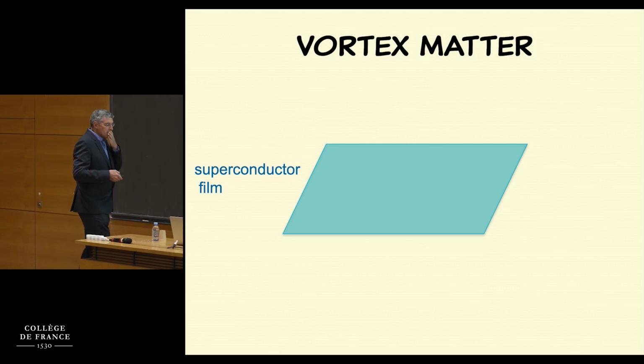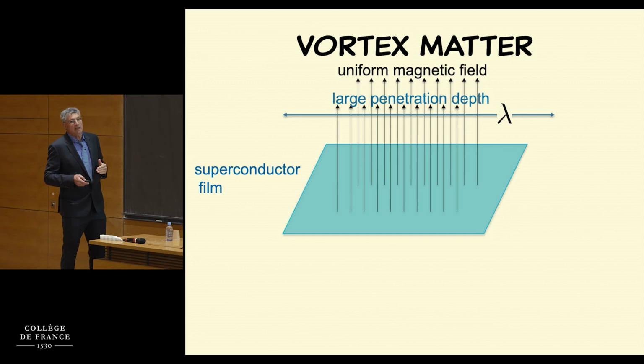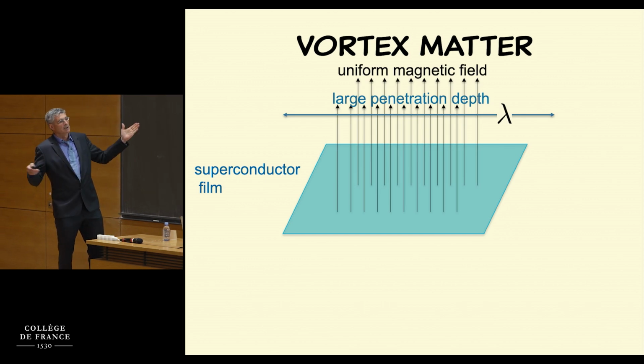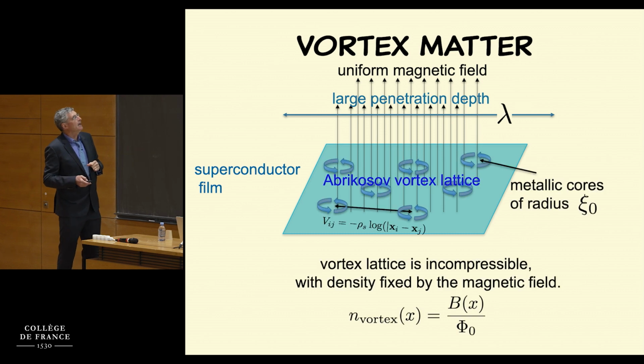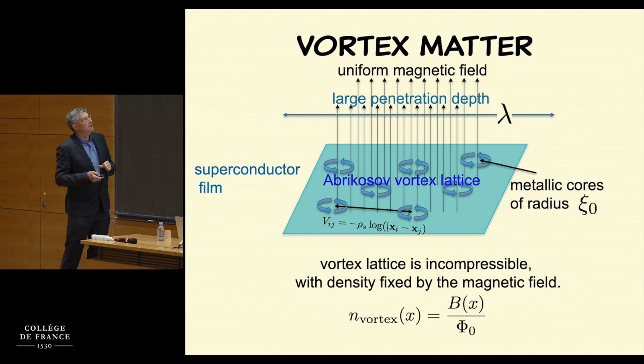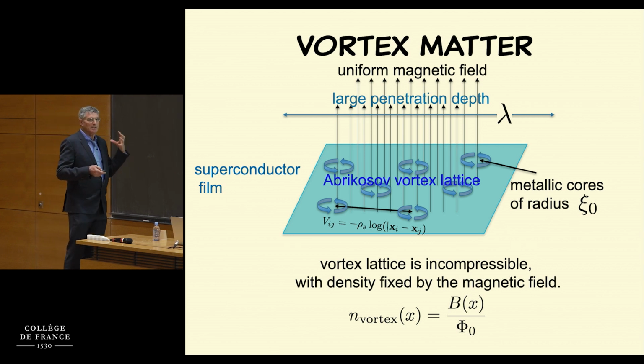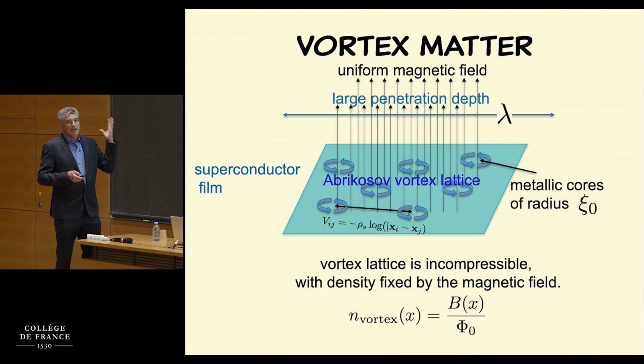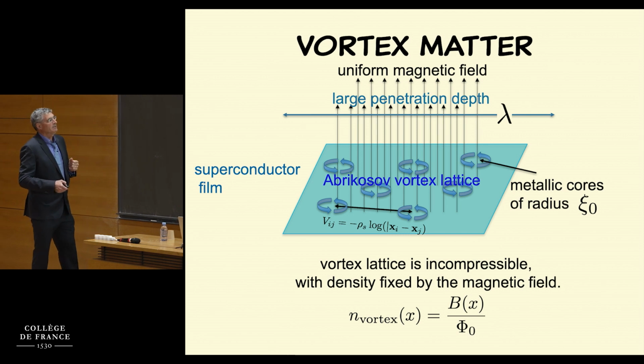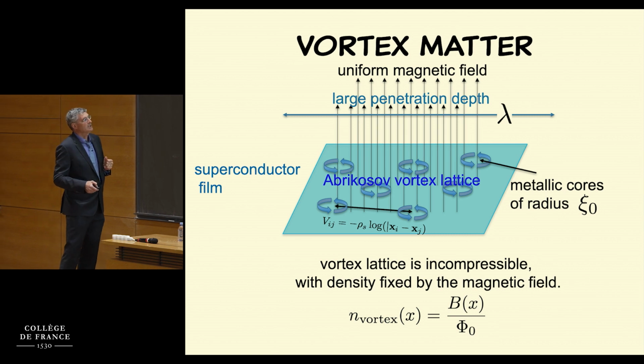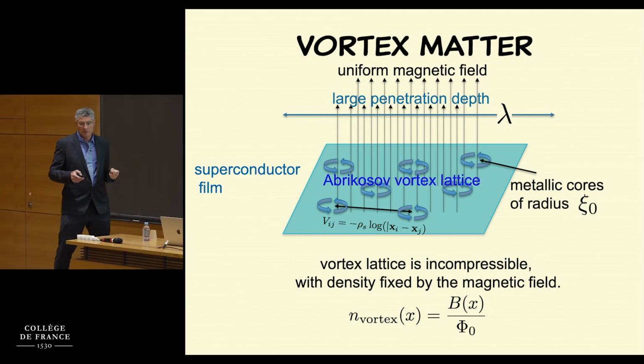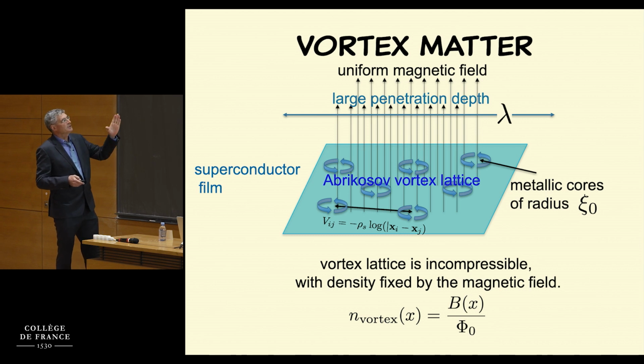Okay, what is vortex matter? Vortex matter is you take a superconductor, you apply a magnetic field to it, you make the system very thin so the magnetic field penetrates uniformly into the film, and that creates vortices. What is important is, because of the stiffness, because of this property that I talked about, it doesn't allow any number of vortices. It allows exactly the number of vortices to be equal very, very closely to the size of the magnetic field. That relation, which is essentially saying the vortex lattice is incompressible and it's completely determined locally by the field, is something that will tell us how many vortices we have if we put a field on a system. Okay? These are vortices of the supercurrent. It's not flux tubes, you know, of the magnetic field.